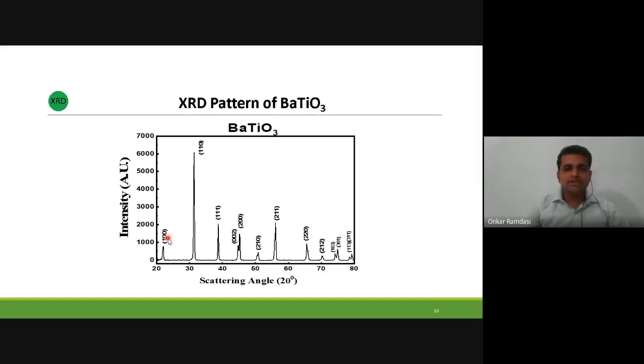In this case, you can see there are different planes which are indexed starting from 100, 110, 111. You can see the splitting of 002 and 200. That is the characteristic fingerprint for the tetragonal structure. You can see 002. So in this case, a equals b, not equal to c. In particular materials, again, this is a rough technique; you have to perform the Rietveld refinement in order to get exact parameters. But roughly, I can say this is the tetragonal structure. So BaTiO3 is obviously a tetragonal structure.